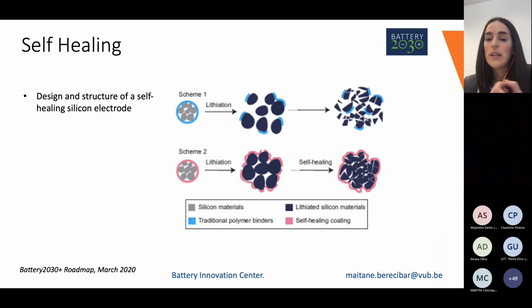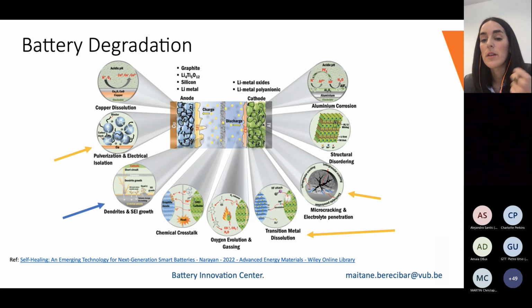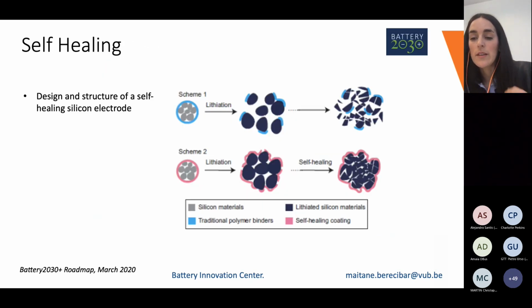So with this self-healing idea, what we can do is use a self-healing coating that will be applied on those layers, and then we can protect that material so that even though the battery will continue charging, discharging and expanding, it will create this protection layer. So this is what self-healing consists of. Here is an example with silicon. However, as we were explaining, many different things can happen. So many different self-healing functionalities are now in the research area.